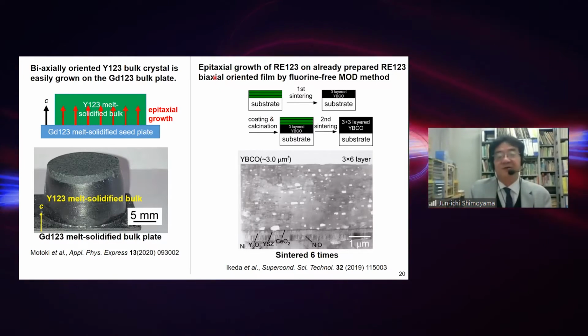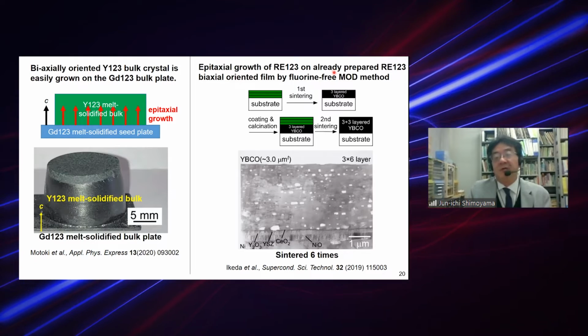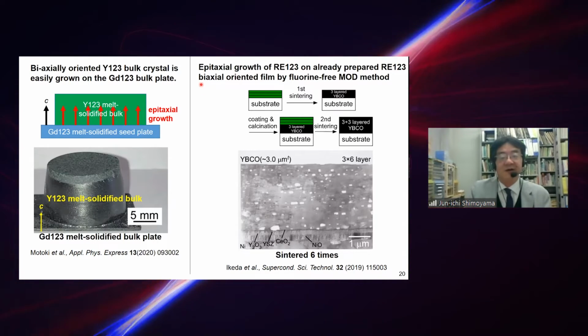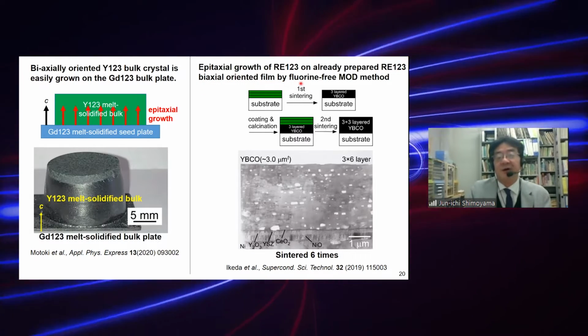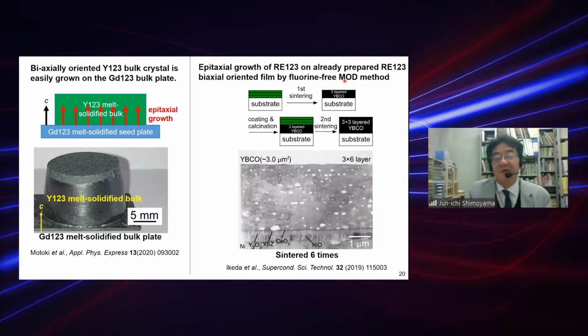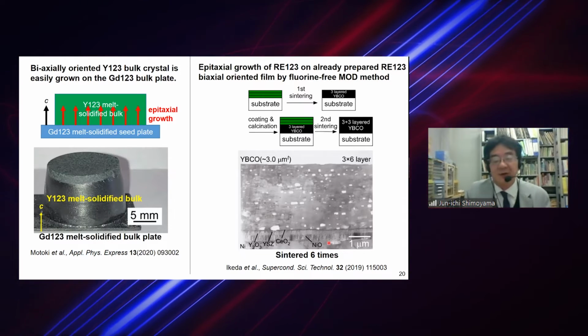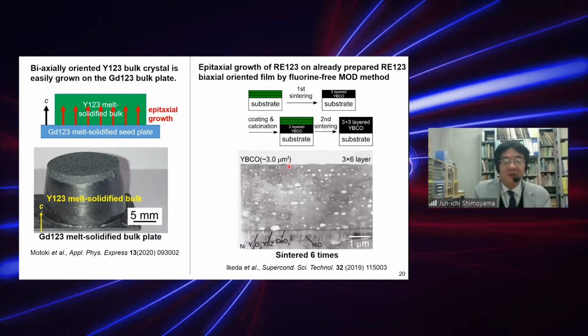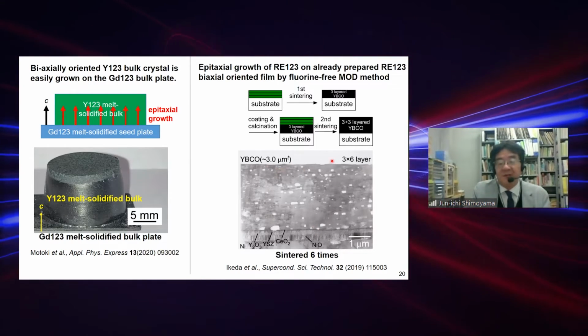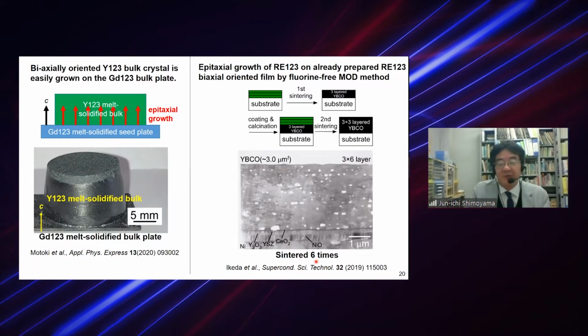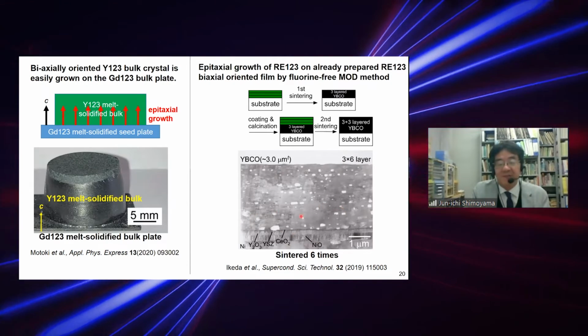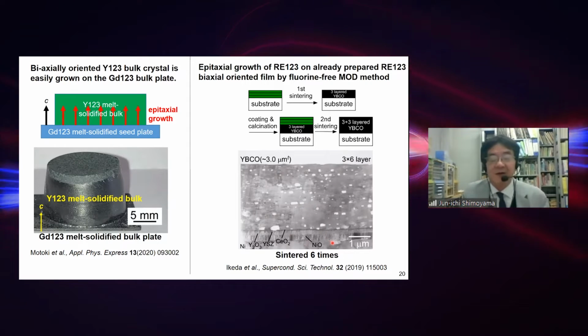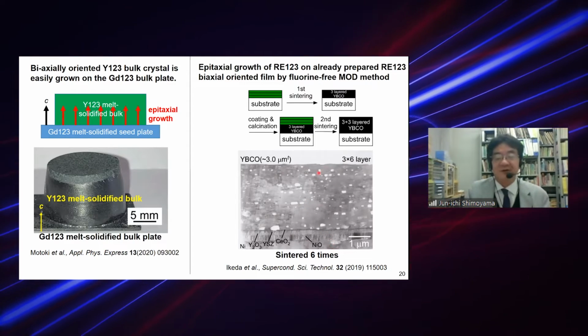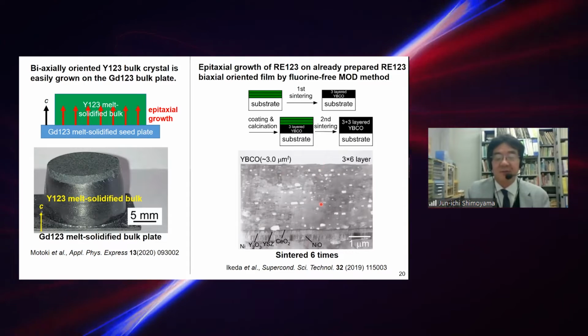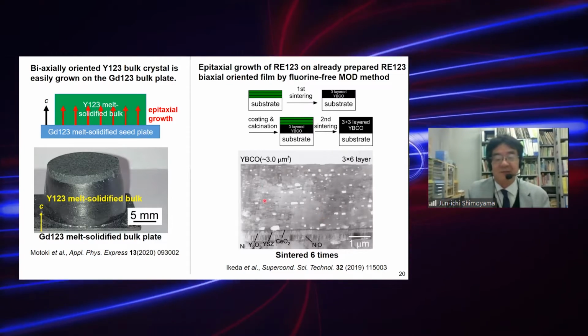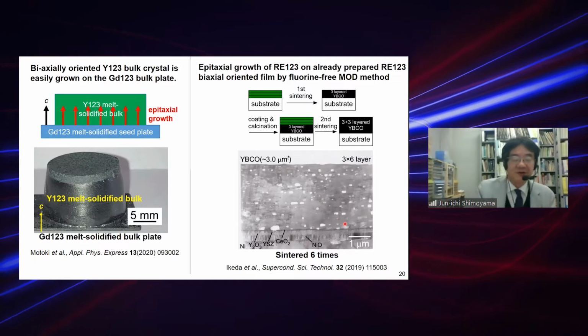On the other hand, epitaxial growth of 123 layers on an already prepared 123 biaxially oriented film by the fluorine-free MOD, metal organic decomposition method. In this case, the total thickness of the film is 3 microns, but this sample was sintered 6 times. Sintering, painting, sintering and painting, we repeated 6 times to obtain such thick films. But the crystal orientation is the same all over the film. This is a hint.